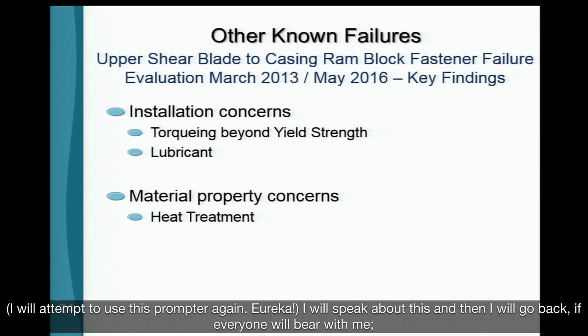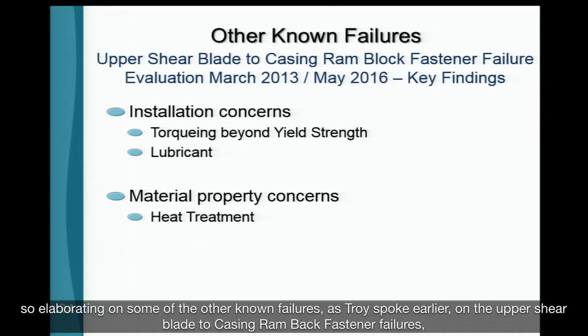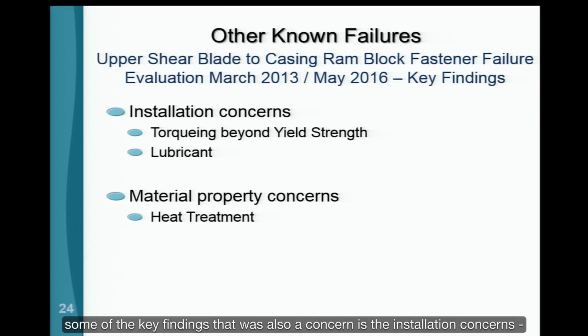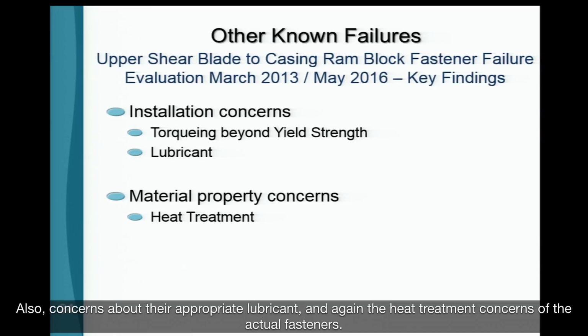So elaborating on some of the other known failures, as Troy spoke earlier, on the upper shear blade to casing ram block fastener failures, some of the key findings that was also of concern is the installation concerns. Were the fasteners consistently applied in the right torque manner? Some of the fasteners were torqued beyond the material strength, the yield strength per the spec. Also, concerns about the appropriate lubricant, and again, the heat treatment concerns of the actual fasteners.